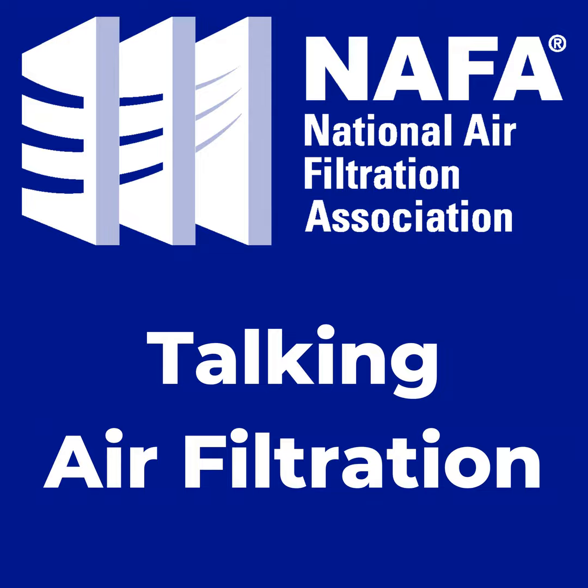What I always describe is that a nanofiber is about 1,000 times smaller than a piece of hair. And when people ask what that means, obviously you can't see something 1,000 times smaller than a piece of hair. When you use electron microscopy, like the image I have up here, you see a piece of hair compared to nanofibers. This is a PTFE membrane. You can see the hair is about 60 micron in diameter, and the nanofibers there would be about 60 nanometers. So a lot of the interesting properties that come from nanofibers are based on this really small fiber that makes up the fiber mat.